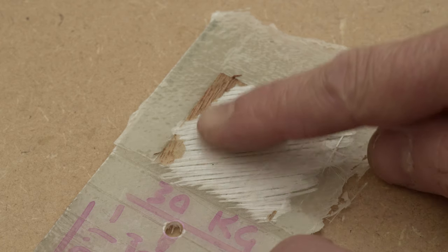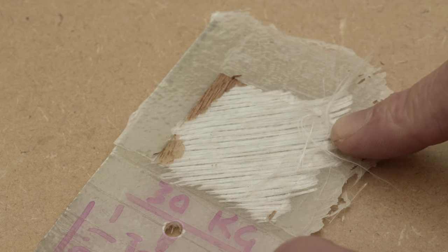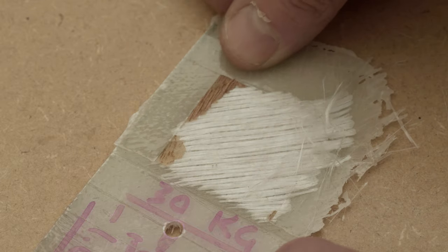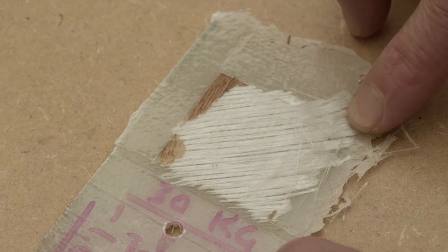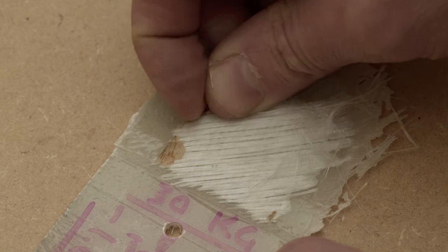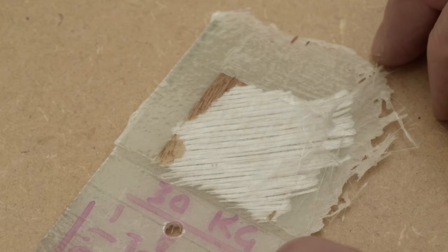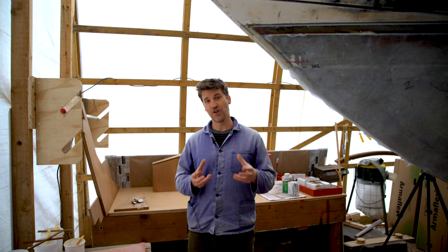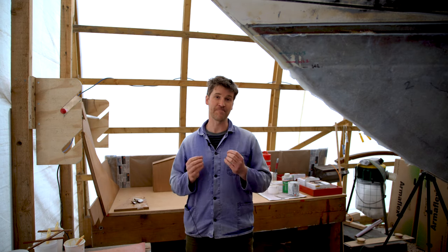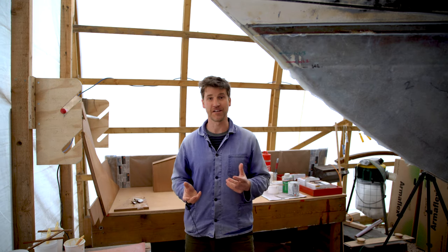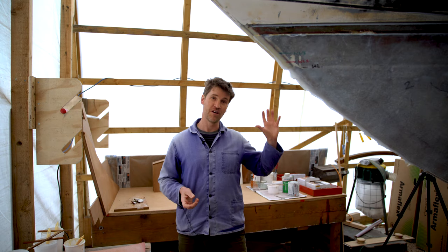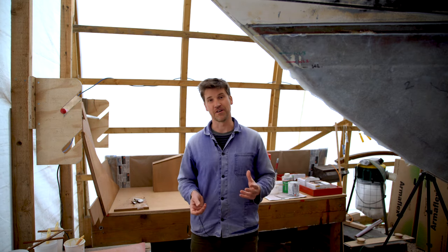With the epoxy tab, the actual fibres of the biax cloth have torn, and also some plywood has started to fail. Again, this shows that the actual bond was stronger than the surrounding materials. Now we've got this data, how can we apply that to make better decisions about which resin combinations to use in the general repair and maintenance of our boats?